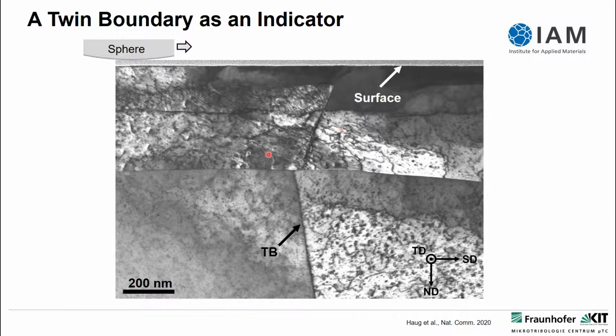After the tribological load, this twin boundary is tilted. It's tilted in the sliding direction, to a degree of alpha, as we can see here. So we have tilted the twin boundary in sliding direction. We also see this dislocation trace line phenomenon, actually two: a lower dislocation trace line and an upper dislocation trace line. What else do we see?